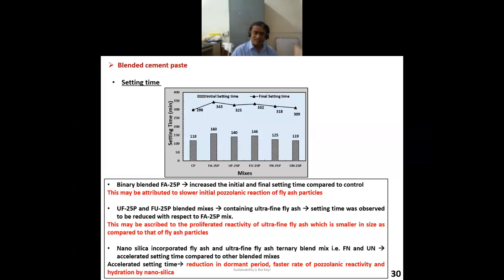Now we have done some research, which I have not plotted here. If you are replacing only nanoparticles, there is a significant reduction in the setting time because of the faster hydration reactions. And if you go with only nanoparticles, it is very difficult for the mason to work with the material because it will not give much time. So the initial setting time reduces drastically.